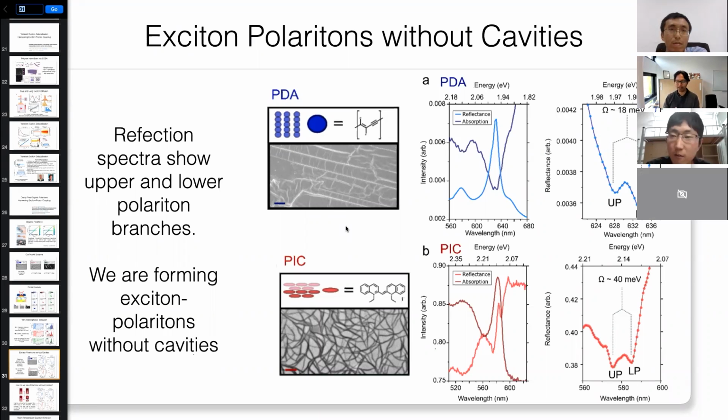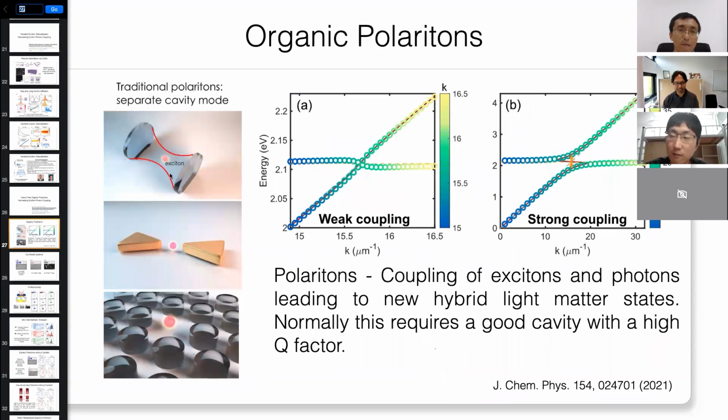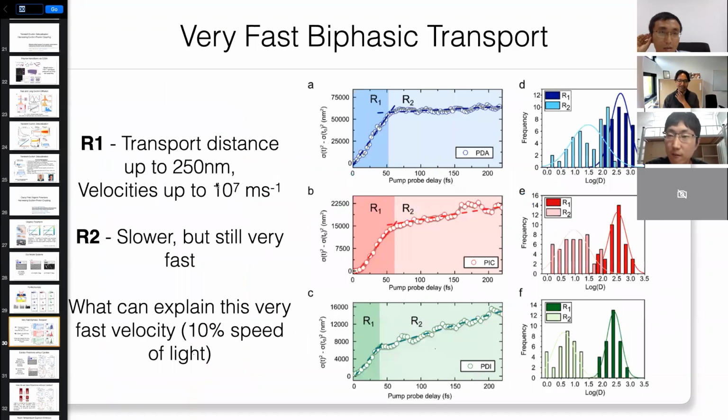But essentially the main thing is to have strong absorption such that you can confine a little bit of that light mode, right? So if you think about what a good cavity looks like, some of these cavities will have a Q factor of like 5,000, 10,000, 100,000, etc. When people do quantum electrodynamics experiments in very high Q cavities, they're dealing with Q factors of 100,000. We are dealing with a Q factor of like below 10, so it's a very, very bad cavity. It's hardly a cavity at all, but it's enough of a cavity that you can actually move the exciton so fast.